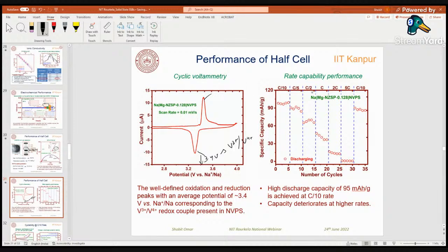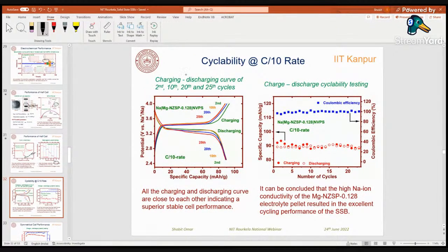We did the rate capability testing, and we obtained a discharge capacity of 95 milliampere hour per gram at C/10 rate. However, the capacity deteriorates at higher current rates, and there are two reasons for that. First, we are pressing the sodium on the ceramic electrolyte, and that interface is not very good. The other is that we still have a low ionic conductivity solid electrolyte. We did the cyclability testing at C/10 rate, and the performance was very stable till 25 cycles. You can see the solid electrolyte works very well at C/10 rate.